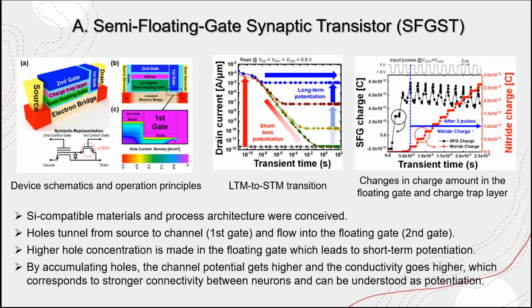Device schematics and operation principles can be explained in the first figure, and the long-term to short-term transition can be found by simulation, like this transient time simulation, where the amount of charge in the floating gate and nitride layer is depicted as a function of the transient time. The semi-floating gate plays a role as the short-term memory storage. After a certain number of pulses, it becomes easier to push the temporarily stored electrons or holes into the nitride storage layer at smaller operation voltages.